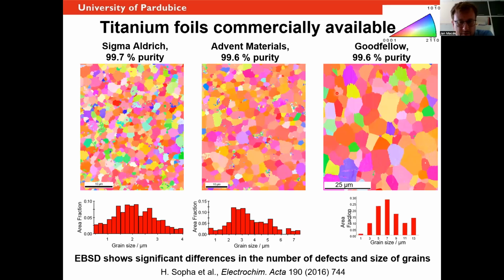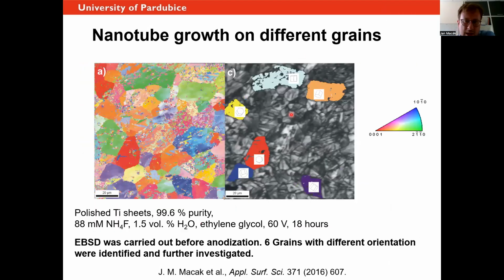I can already tell you that the good news is that not much happens. This technique is so universal that in principle, no matter what titanium you take, and also almost no matter what purity you take, it still has to be, of course, the majority titanium, you will have tubes at the end. And you can see here these EBSD patterns which show you the grains. So of course, every titanium from every supplier has slightly different grain structure. The grains have different orientation, different size, but nevertheless, we looked at it in details and we found out that there are always tubes growing on every single grain.